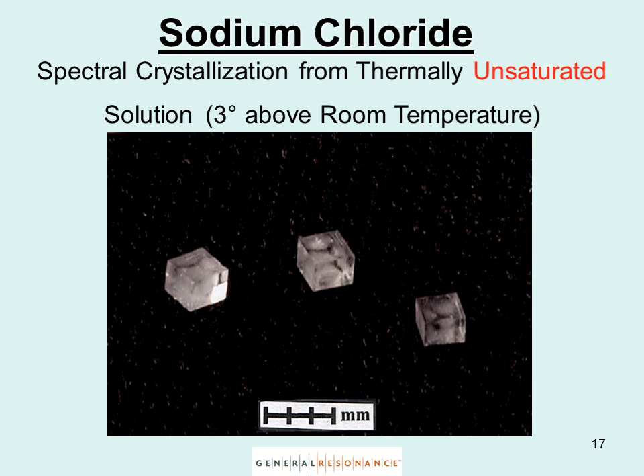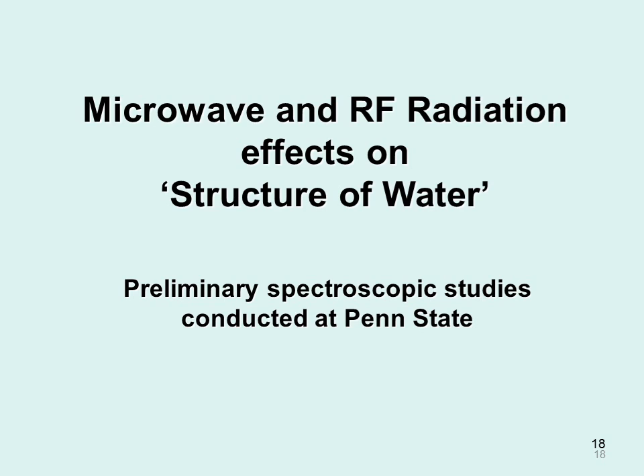I'm skipping a lot of stuff which will be in the paper, but we are growing millimeter size crystals. These are very perfect actually, they're centimeters when they're grown, from thermally unsaturated solutions. So we are doing it where there's a 3 degrees above room temperature, and yet we are growing crystals. So what am I doing? When I saw that, I said we are changing the thermodynamics. The saturation of NaCl in illuminated water is lower than in regular water. So now let's go from those photons, say about 1 eV, 1 or 2, 3 eV, down to 2.45 gigahertz microwaves. You'll see what happens.